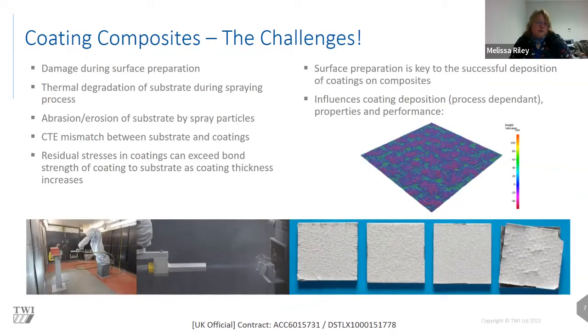Obviously, when you come to being able to coat composites, you have a bit of a challenge in that you have a thermal process combined with a low thermal tolerance substrate. So a lot of the work that I've been involved in historically has been looking at how we are able to prepare coatings onto composites, and avoid damaging the composite significantly when we prepare the surface for coating. Thermal degradation, abrasion and erosion from spray particles can be a problem, as well as CTE mismatch and residual stresses. So basically, we've got a lot of know-how in terms of how to prepare and deposit coatings onto composites.